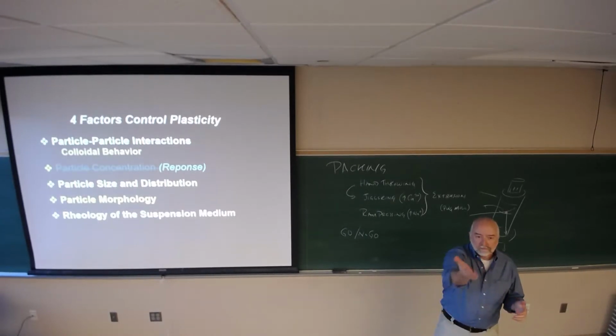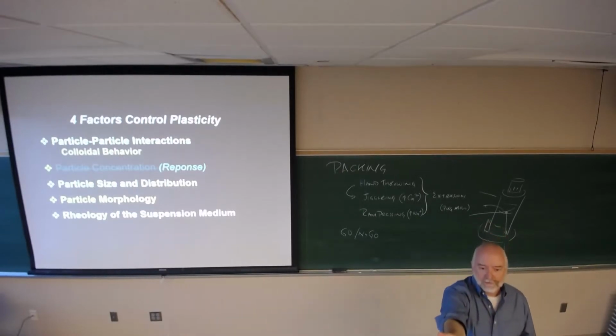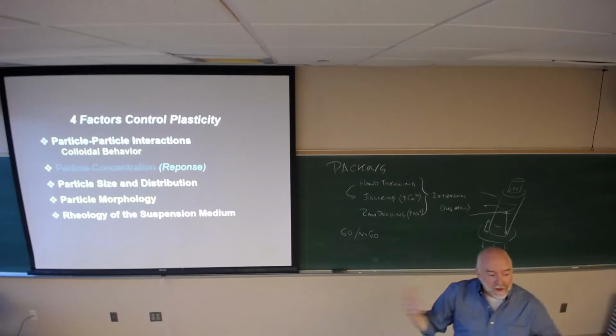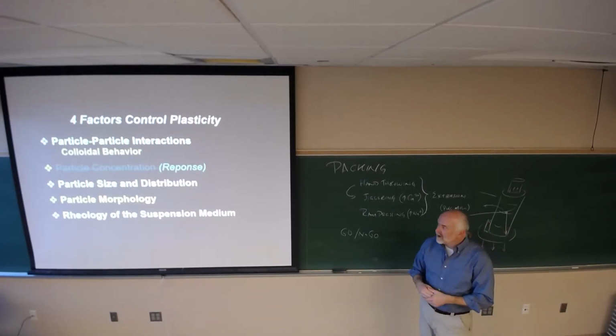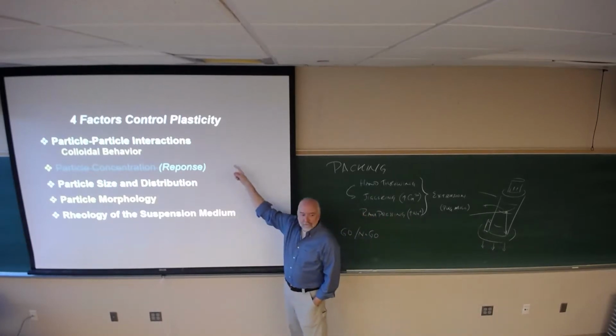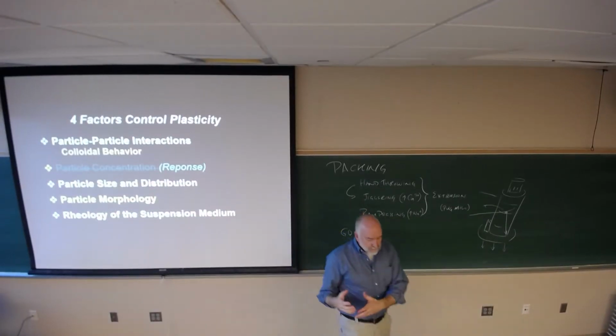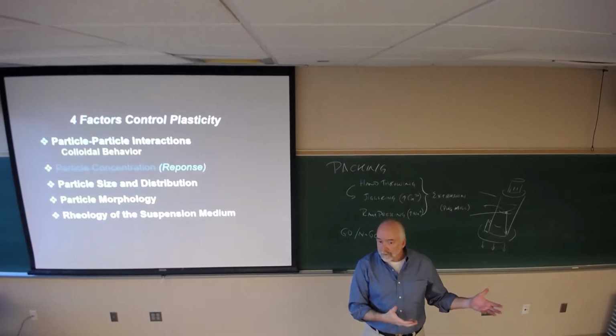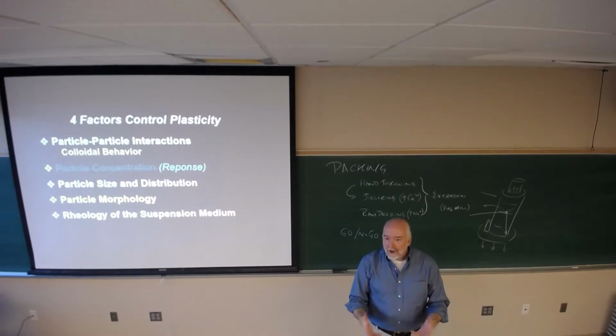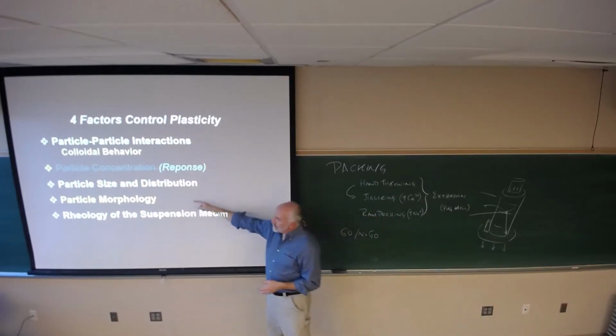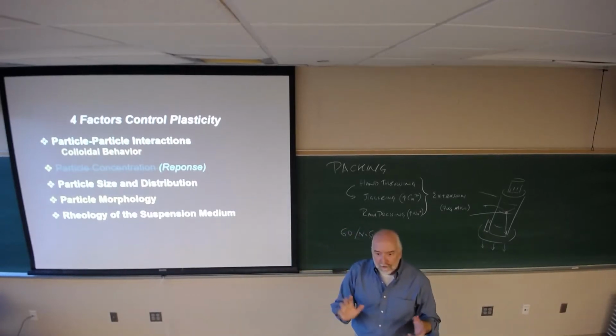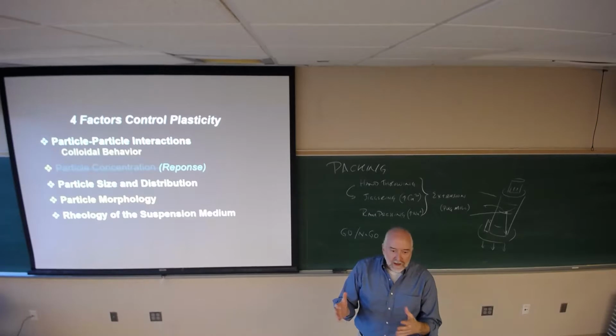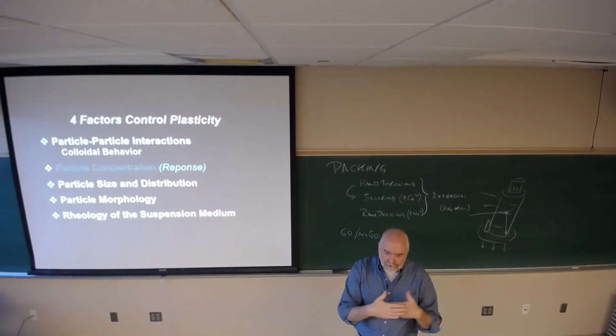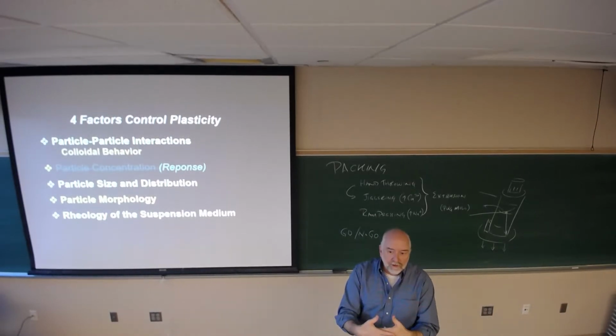How do I improve the packing? Yeah, if I add dispersant, I improve the packing, I require less water, right? So my particle-particle interactions are still valid. My particle size and distribution, that's the situation of clay by itself versus clay plus quartz and feldspar, right? When I do that, I get better packing. Therefore, I require less water. If I go, this morphology thing for clays turns out to be critically important. But if I have all spherical particles, I get one packing. If I get particles that are shaped and they're able to nest or fit better within each other, within the packing, right? When they start to align, I see an improvement in packing, right? This last one actually gets to go away because we work with water.